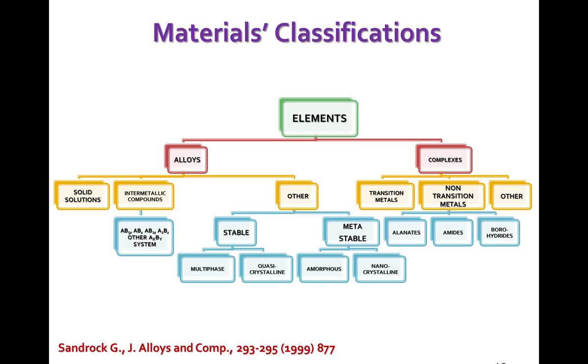So then we went on to other systems like some of the stable and metastable systems like multiphasic compounds, quasi-crystalline, amorphous and nanocrystalline compounds. These compounds do have some interesting properties for storing in the grain boundaries and grains and multiphasic natures. However, the gravimetric capacity is not yet improved. Therefore, a new sort of complex compounds was introduced by a scientist called Bogdanovic in Germany. That's sodium aluminum hydride. He throws some titanium into the sodium aluminum hydride. That becomes more like a catalyst for the whole industry. The whole academic community started working on those complex materials.